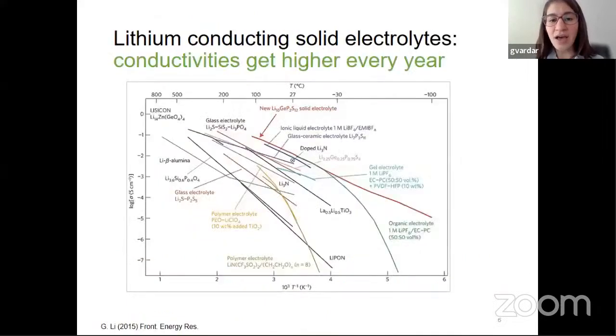However, there are some lithium conducting solid electrolytes that have lithium conductivities that are close to the liquid case. Here we are seeing the benchmark, this organic electrolyte, the green spot or green line. You can see that all of these other solid electrolytes are trying to get close to it. So there are some solid electrolytes that can have the same power density, the same conductivity, meaning the speed to shuttle lithium back and forth.